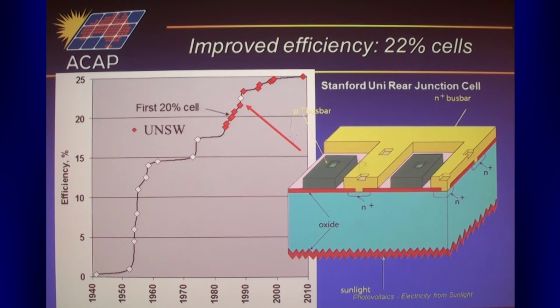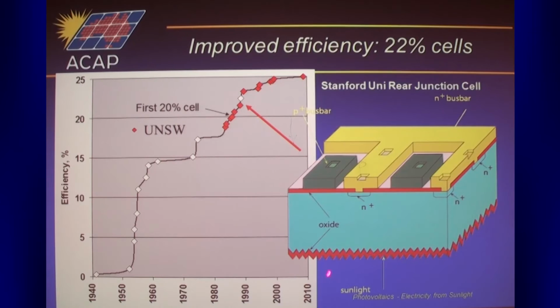Where is that? It seems to have dropped off this drawing. Oh, it's underneath these regions here. So you can't see it in this drawing, but there are little P-type doped wells here. So all your P-N junction activity is on the rear. It turns out you need very good material for this structure to work, because most of your carriers are getting generated near this surface. They've got to find their way over to this rear surface to work.